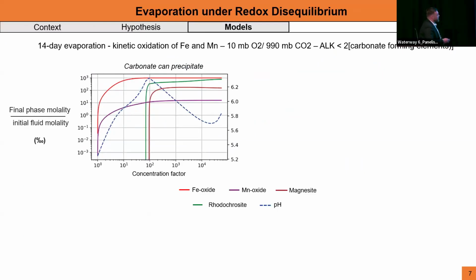But the idea here is that you concentrate a solution that starts from a relatively dilute concentration, like river-type concentration, and you do the oxidation kinetics at the same time that you concentrate. And what you observe here is that you initially raise the pH, and as you raise the pH, your iron is going to be oxidized completely. Here it's iron oxides precipitating, which is expected because you are still at 10 millibar of oxygen. But on the other hand, your manganese starts to be oxidized, but at some point it stops being oxidized because you have the precipitation of carbonates. And these carbonates are going to remove the alkalinity of the solution, and you're going to lower your pH, and you don't oxidize much. Less than 1% of the manganese in the solution.